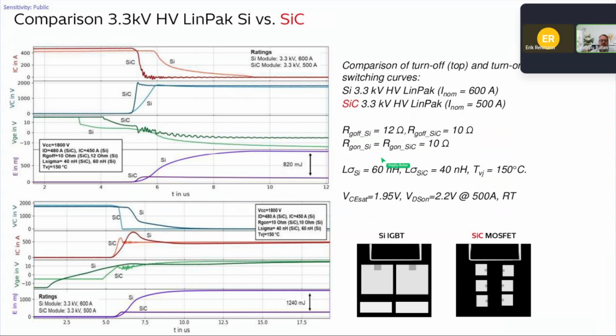And this we see very well. This is exactly what we did. So we took these two modules. So the module that I showed in the beginning, which we are launching for traction application in silicon. And we put the curves exactly on top of each other with a half populated module. So from current rating, they are quite similar. So 600 versus 500 or 480. But you can see here the difference in switching speeds, right? Both in terms of turn off and turn on, and also energy.